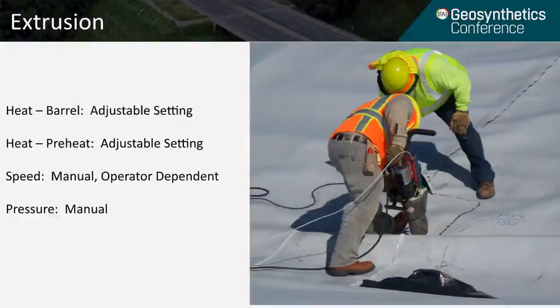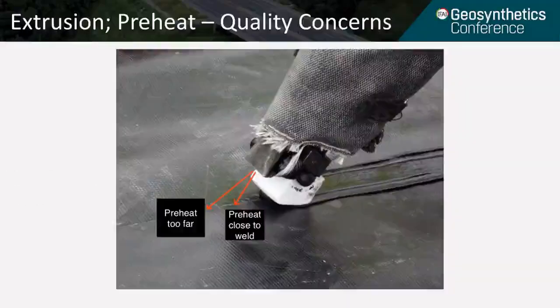So you want to have a firm substrate below it. Welding over a wrinkle is a bad idea because it doesn't have a firm substrate, and it results in an inferior weld. This picture illustrates the preheat I talked about on the previous slide. It's a close-up picture where you can see the preheat ahead of the barrel, where the welding shoe is there. The white is the welding shoe, Teflon welding shoe.